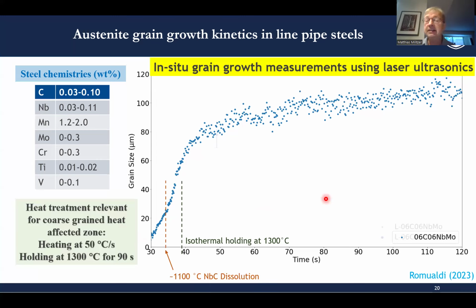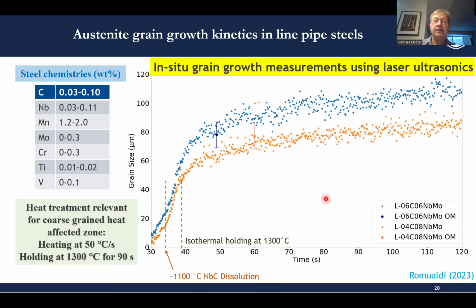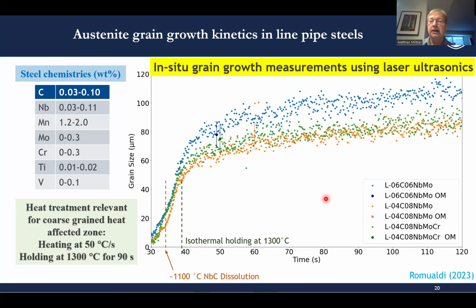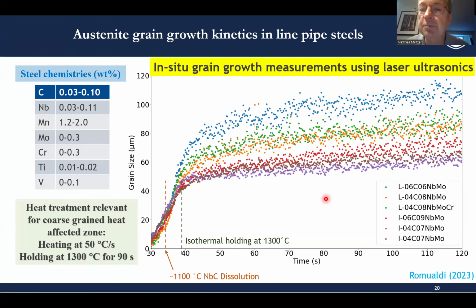We validate now and then these measurement data with ex situ microscopy, either classical optical microscopy, or now increasingly using reconstruction of the austenite structure from EBSD mapping. And once we have done one test, we can do a second test, a different steel, and a third test, etc. And I show you here 6 tests, and this is what you can do basically in an afternoon. And you can compare this now, how long it would take to create even portions of these curves with classical ex situ grain growth studies.